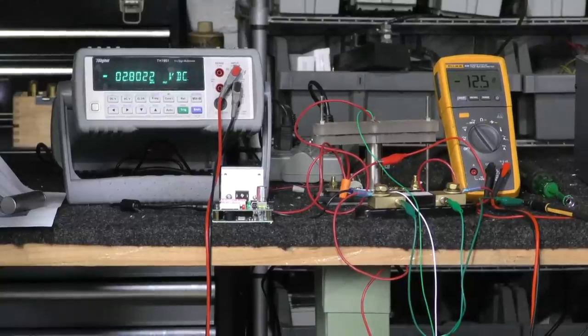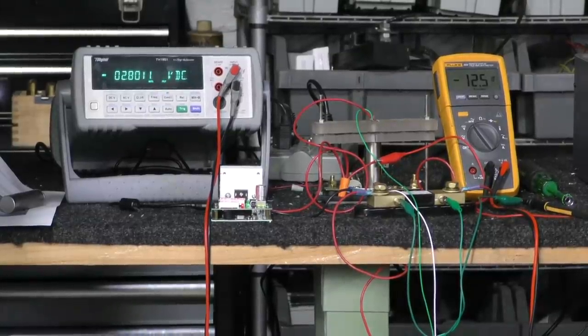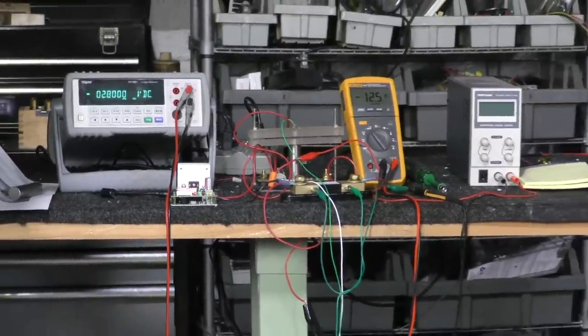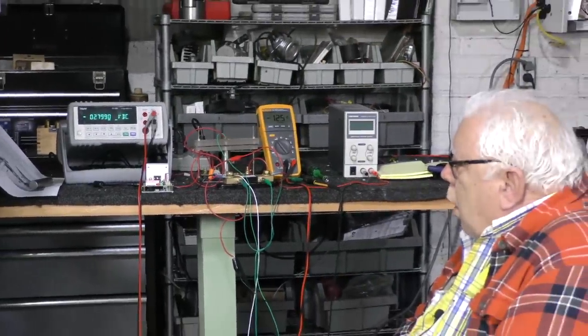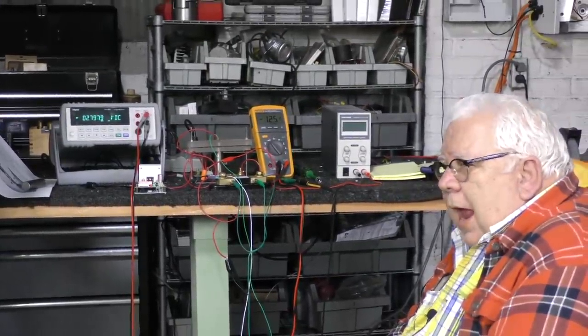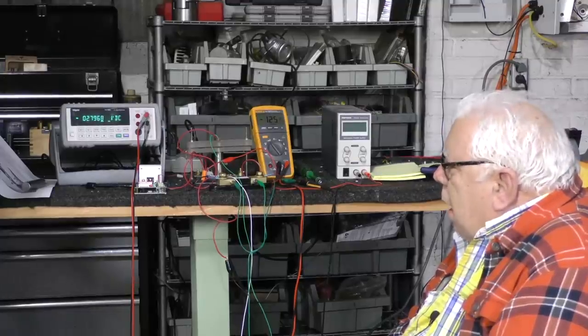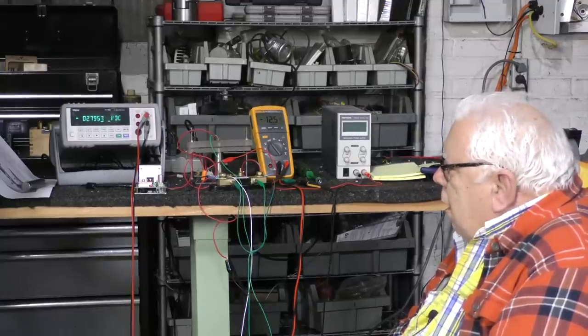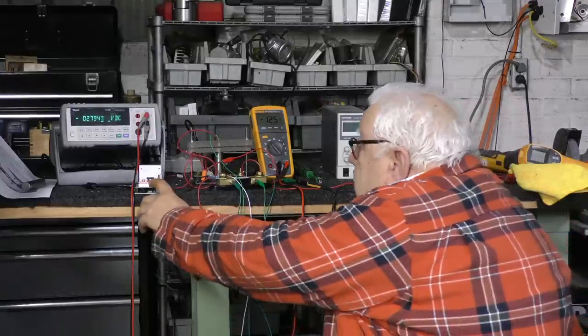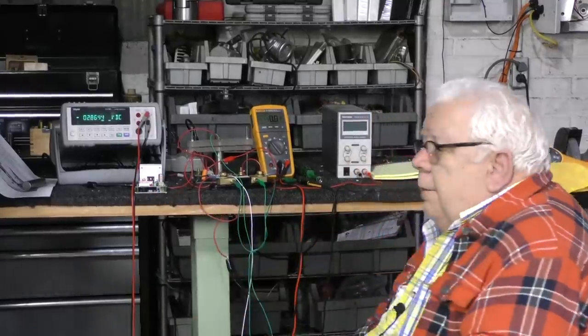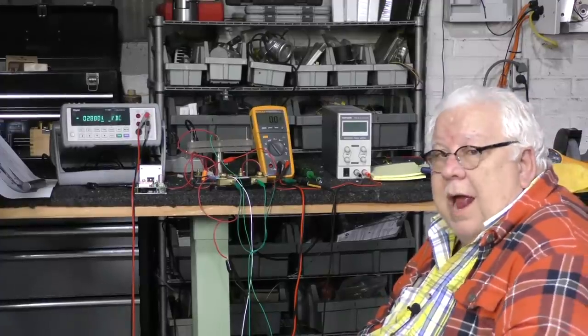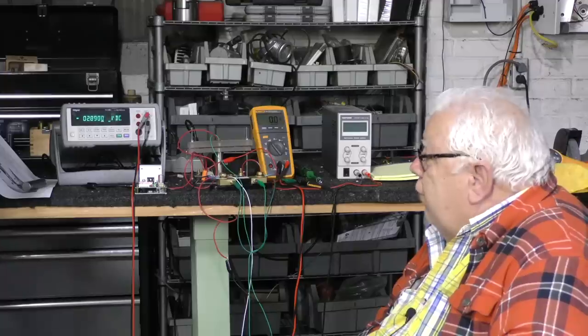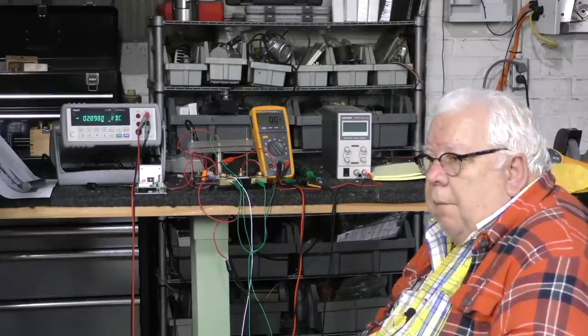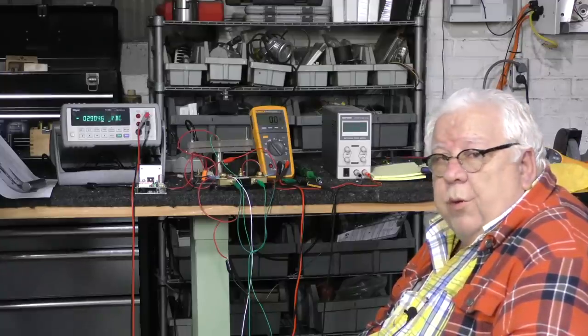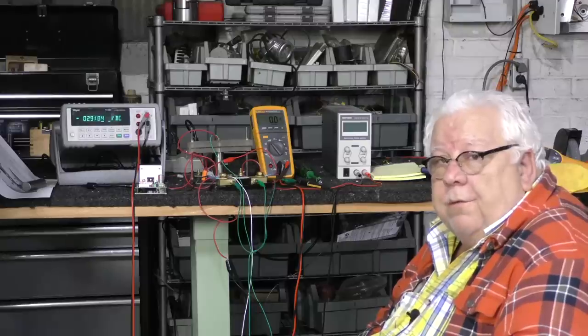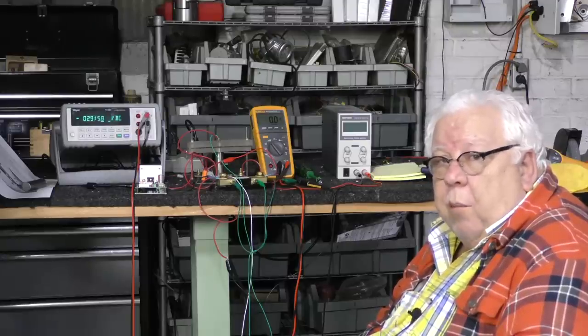And I think the very reasonable 0.25C, 1.25 amps, is what you would actually probably be using in a Model 3 on a road trip. And we're done right at 3.5 hours. And that sort of indicates a 4.375 amp hours, which I find quite disappointing.